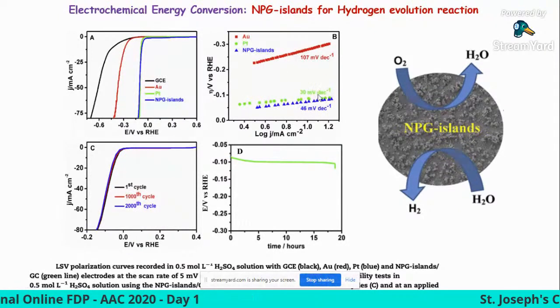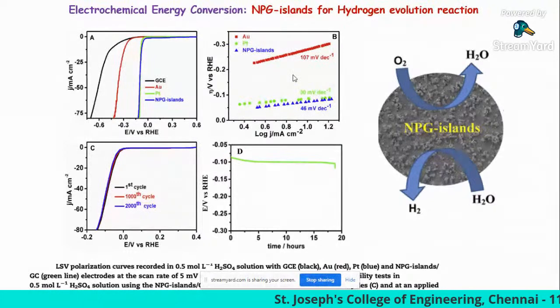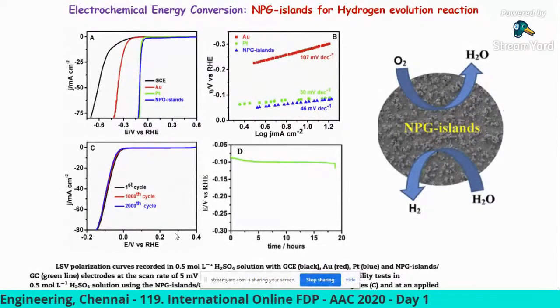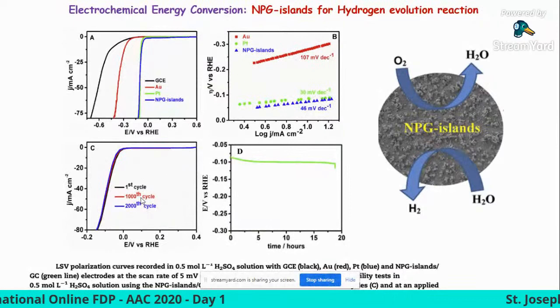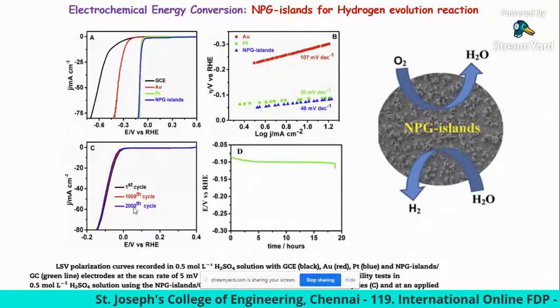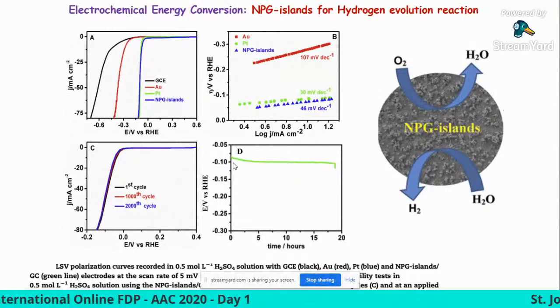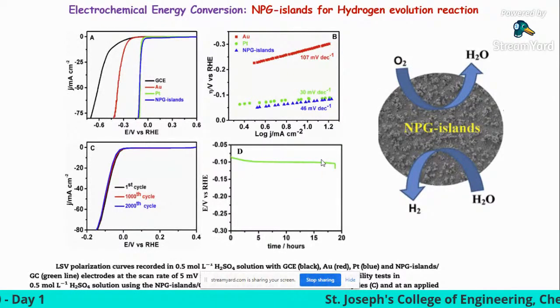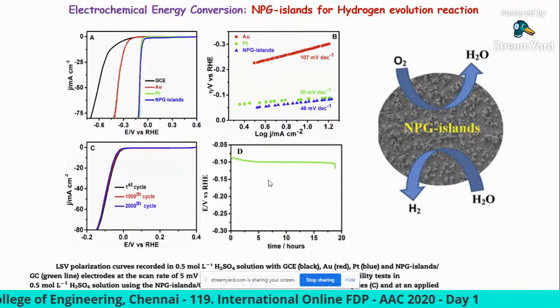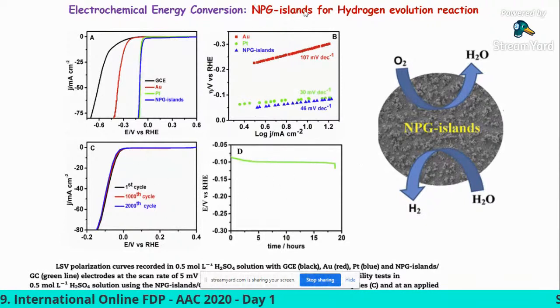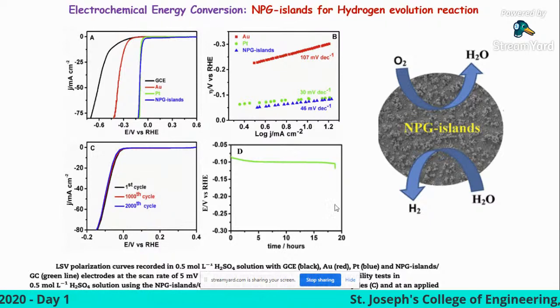And this is the corresponding Tafel plot. From this Tafel plot, we can define the mechanism, what kind of mechanism takes place at the electrolyte interface. These are the stability studies for 1000 cycles and 2000 cycles. This is the initial cycle, and after 1000 and 2000 cycles it also indicates a similar behavior. And this is the amperometric performance for recording the durability of the catalyst. Even up to 20 hours, it shows a similar current signal. So this research indicates the nanoporous gold island is also suitable for hydrogen evolution reactions.